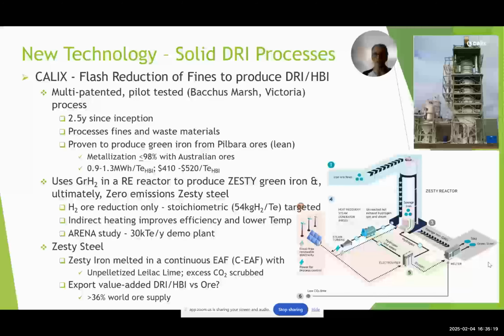Another new process with solid DRI is Calix. It's a flash reduction of fines to produce the DRI, multi-patented, pilot tested, and it's 2.5 years since its inception. It processes fines and waste materials, proven up to 98% metallization with Australian ores, and up to 1.3 megawatt-hours per ton of HBI, and approximate pricing between $410 to $520 depending on further development.